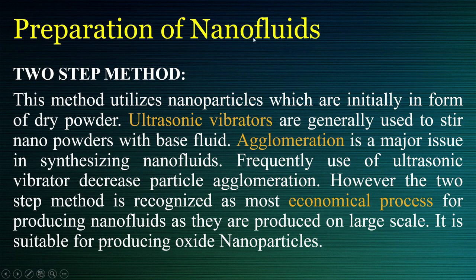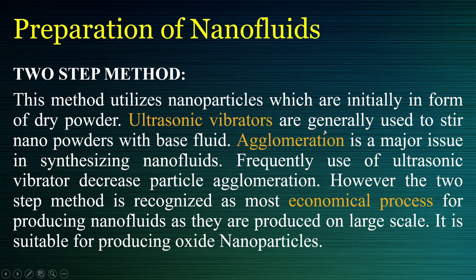Now for the preparation of nanofluids, there are two methods. The first is the two-step method. In this method, nanoparticles in dry powder form are first added to the base fluid and then ultrasonic vibrators are used to stir the mixture. The continuous vibration prevents agglomeration — meaning the particles don't settle down — and the nanoparticles mix well in the base fluid.